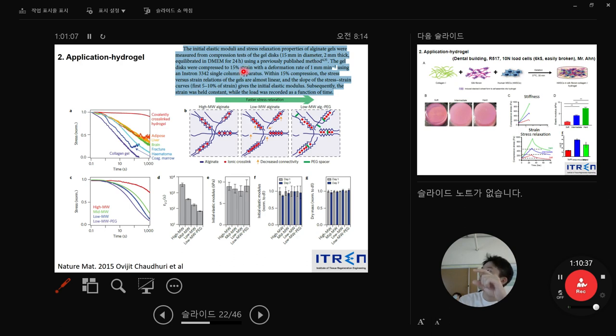The thickness goes down to 1.7 millimeter from the original 2, which is the 15 strain at compression, with a deformation rate of 1 millimeter per minute. This is very important. When you do some mechanical property test, the rate of the Instron load cell is very important, because depending on this rate, your measured strength can change.